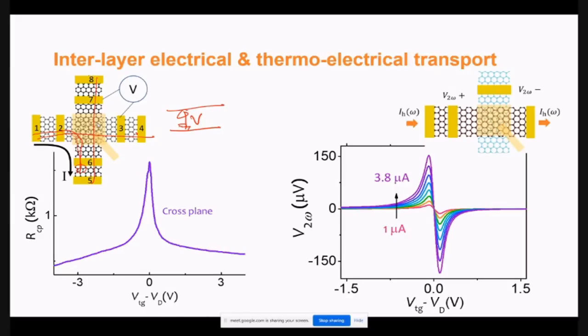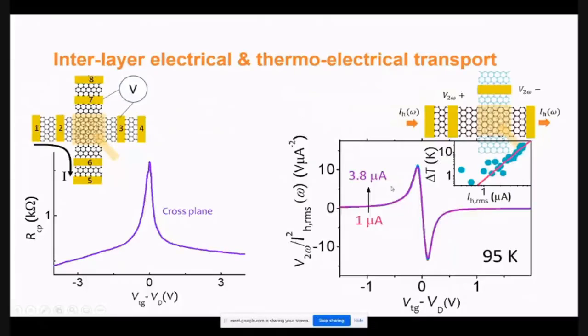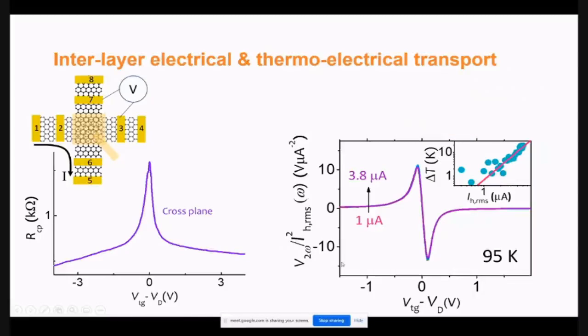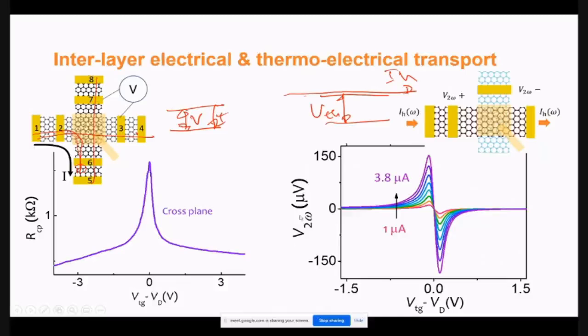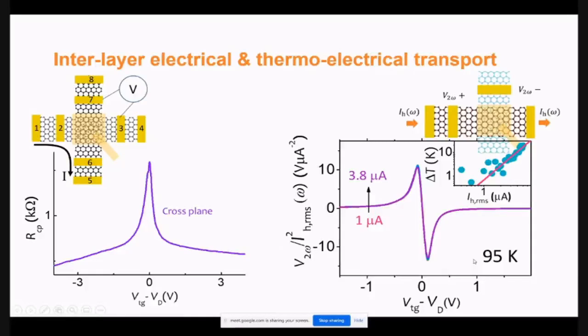Now, if I want to measure the thermoelectric potential, I have an upper layer and a lower layer. In this case, I have only one current in this direction, which is the heating current, and now I am measuring this voltage, which is called the thermal voltage. This voltage is plotted here, and as you increase the heating current, this voltage increases continuously. This is from 1 microamp to 3.8 microamp. If I scale this voltage by the square of the heating current, I get all curves exactly collapsing on each other, and that tells us that this is because of thermal, or heating, origin. So I'm transferring heat from the upper layer to the lower layer.